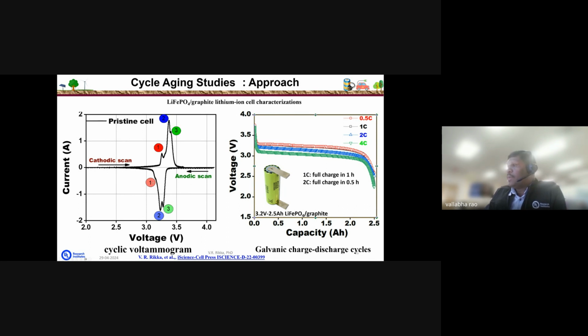With this cyclic voltammetry, we can identify the main redox reaction mechanisms taking place within the cell, what the operating voltage range is, and up to what voltage we can operate this cell. Here we can see that even this LiFePO4 based lithium chemistry showed prominent redox reactions between, for example, 2.8 volts to 3.6 volts. Even if you operate the cell up to 4 volts, we haven't seen any degradation mechanisms.